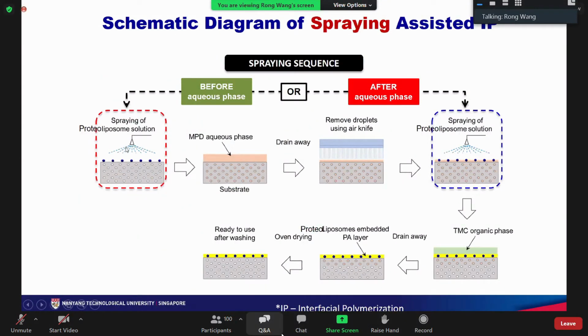Different from the blending method, we use the spraying method to directly load aquaporin on the substrate. As shown in this schematic diagram, there are two options. One is to spray the aquaporin vesicle directly onto the substrate, then apply the aqueous phase and follow the normal procedure. Another option is to load the aquaporin vesicles after the MPD aqueous solution. This means the aquaporin vesicle will load directly in the thin film of this MPD aqueous phase, then apply TMC and go through the interfacial polymerization. We found the after-aqueous-phase option is better because it can keep all the aquaporins inside the matrix, and will not waste any aquaporin and the lipid.